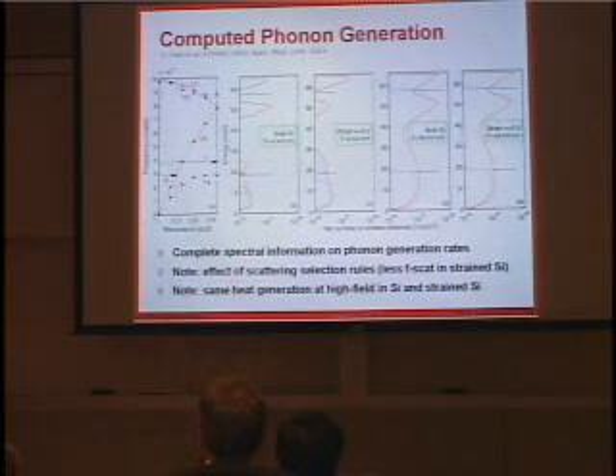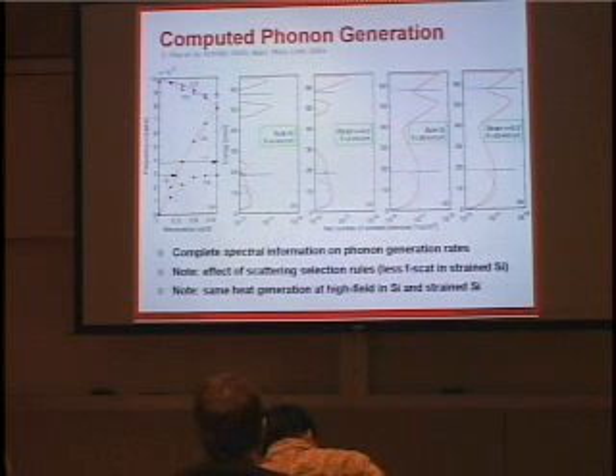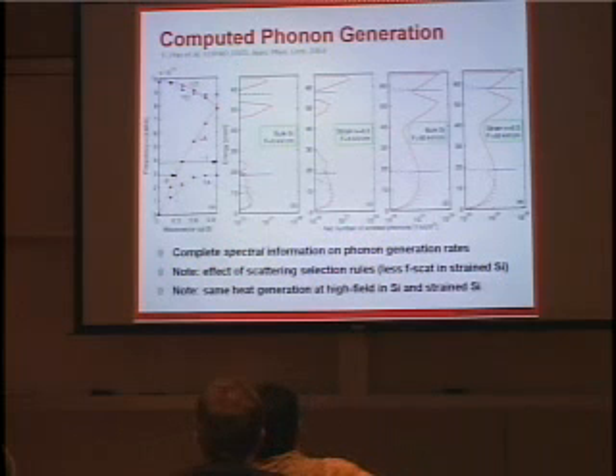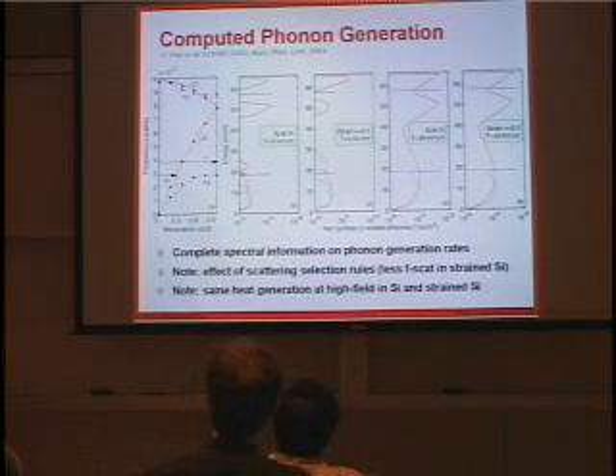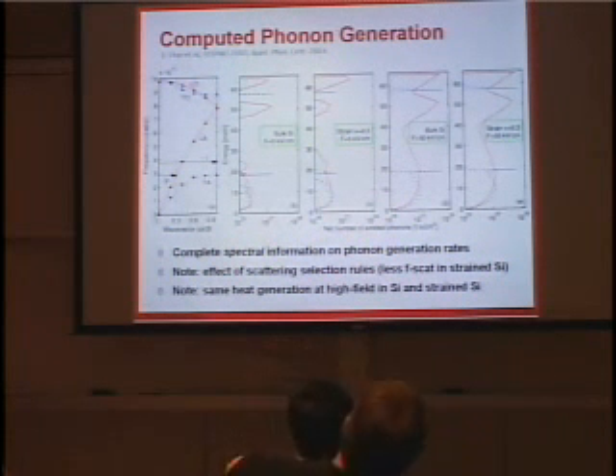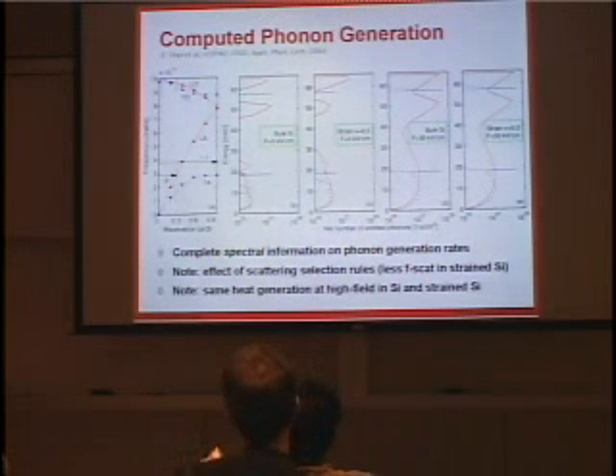So really one of the main results of this work is this computed spectrum of phonon generation in silicon. What I've got here on the left is the phonon dispersion relation, which by now you should be pretty familiar with. On the right, I have the phonon generation rates in bulk and strained silicon, both at low fields, the two middle ones, and the two on the right at high field.